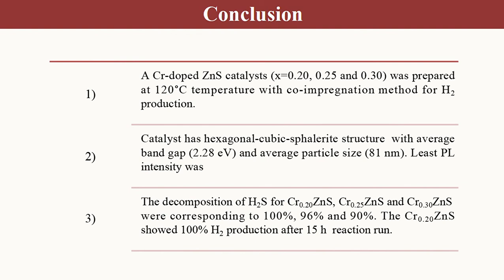Conclusion: a chromium zinc sulfide catalyst of different molar ratios was prepared by the co-impregnation method for hydrogen production. Catalysts have a hexagonal cubic sphalerite structure with an average band gap of 2.28 electron volt energy and average particle size 81 nanometer. The least PL intensity was observed for the minimum doped catalyst. The 100% photocatalytic activity was observed for the less doped photocatalyst.